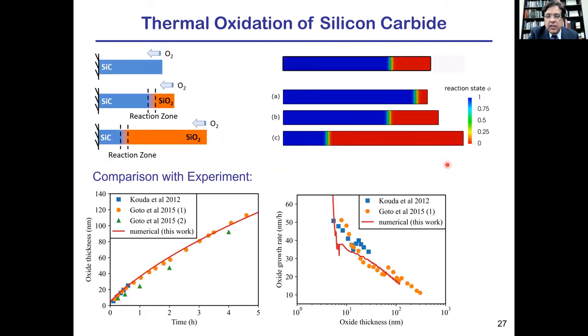This is another test case where we are looking at mechanical material properties that give rise to a steeper front under thermal oxidation. These are different states, and we have plotted oxidation thickness as a function of time. The solid line is our numerical result, in comparison with some published results in the literature. Also, we have looked at oxidation growth rate as a function of thickness, and again, we get good correlation with published data in the literature.